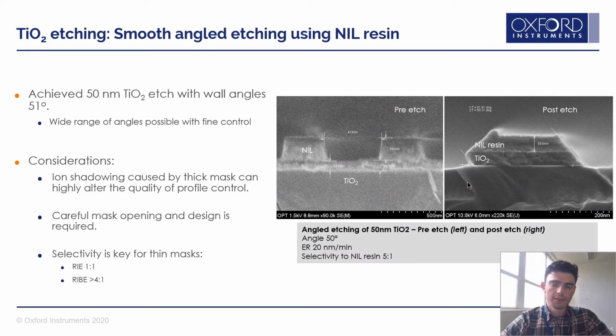Mask thickness will have a significant effect. You're going to have a lot of shadowing, and also the angle of your walls is going to impact what happens in your etch. So carefully designing your mask and carefully opening your mask are two very important steps. Because of this, selectivity is also a big concern. Whereas in an RIE, we might be using 1-to-1 selectivity, in the ion beam, really you want to be above 4, so you can have a nice thin mask. And in the example shown on the right, where we have this titanium oxide, this high RI material, we've got a 5-to-1 selectivity to this nanoimprint resin.